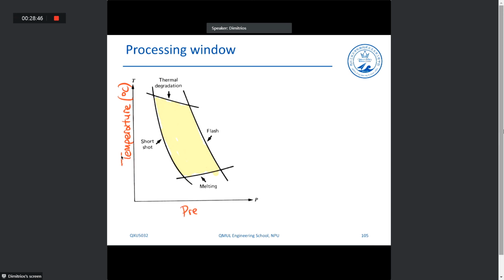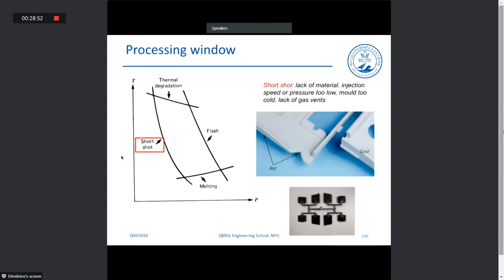So let's have a look at the left side of the processing window, where we have this problem that is called short shot, okay? If we operate at pressures lower than this pressure here, this range of pressures, we are within a low pressure region. So let's say in this region we have low pressure, and a short shot essentially means that there is not enough material that is injected.